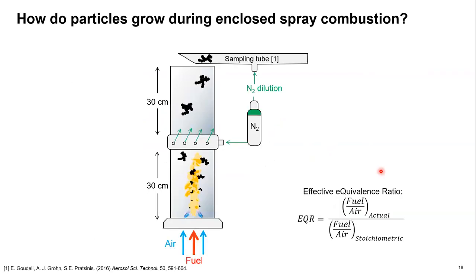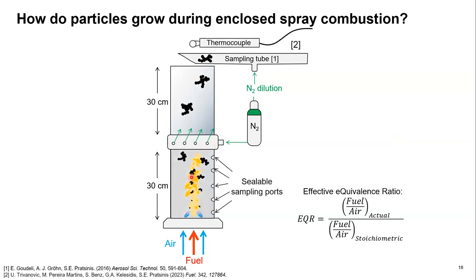So everything that I've shown you up to now has been somewhat of a black box. We changed the equivalence ratio and we got different particles out. However, we didn't understand what was causing these differences. So we then went on to take this research a step further and we replaced this first quartz glass tube with an identical steel tube that had these sealable sampling ports drilled into the side. And so this allowed us to place that sampling tube and also a thermocouple to get the temperature at different heights above the burner and to get then the dynamics of the soot as it travels through the flame.